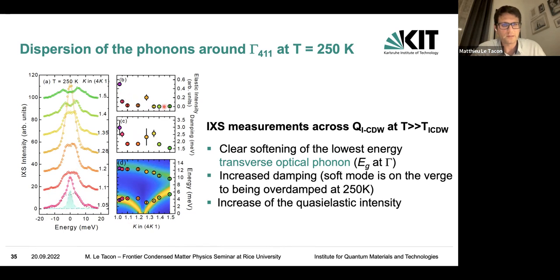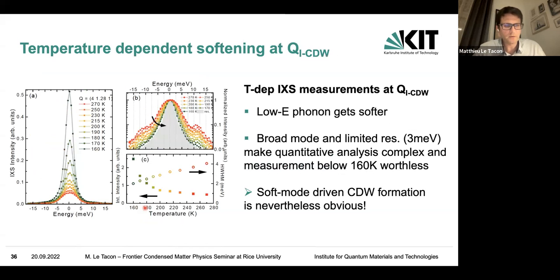And what we find is that the elastic line has some kind of a maximum at the wave vector of the instability. The mode is getting a bit softer, the low energy mode here. That's at 250K, well above the transition. And there's also some kind of broadening around the wave vector of the instability. Now, if we cool down, the intensity at Q_CDW is increasing tremendously. We do have a lot of elastic line here, and below 160K it basically becomes impossible to measure because this intensity becomes too strong.